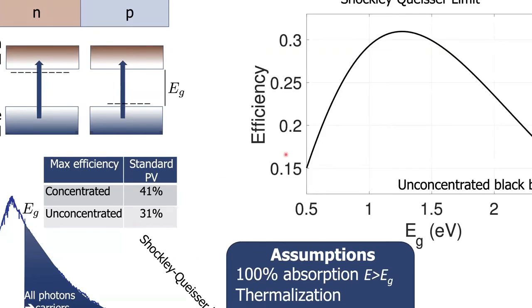So if we just look a little more broadly at the Shockley-Queisser limit, this is for a black body spectrum, a model spectrum for the sun, what you can see is that in order to achieve a 25% efficiency, you really need to consider materials that are between 0.8 eV as a band gap and 1.8 eV as a band gap. And that indeed is basically the range that people look at for solar energy.